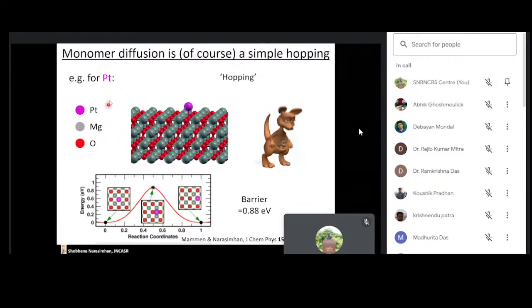So here I'm showing you the diffusion of a single platinum atom, that is this purple atom, on a magnesium oxide support. Okay, and it is diffusing by this process. So this is not just an artistic animation. This is an actual DFT path obtained by using a process where we combine density functional theory with something called the nudged elastic band method. So the particle hops along the surface and we can calculate the energy profile for this.